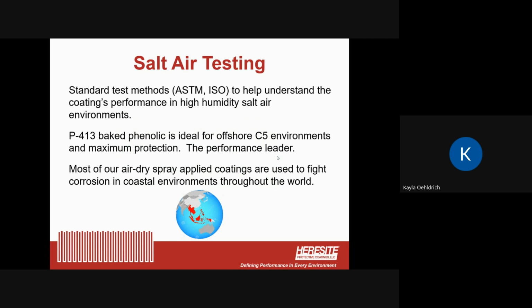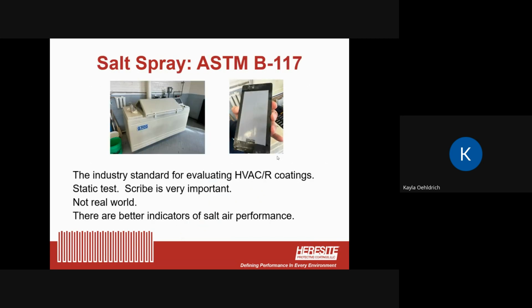Most of our air dry spray products are used to fight corrosion really in coastal environments throughout the world. On the globe, where I've got Southeast Asia, it's basically a bunch of countries that are big islands. That's a particularly difficult environment, and they use a lot of our air dry coatings. The most popular tests that people run into with HVAC R coatings is really the industry standard that's used for evaluating these coatings. Like many of our tests, this is done in-house. The picture on your left, you can see that's our fog machine, which has constant salt air mist that goes over to evaluate the coating.